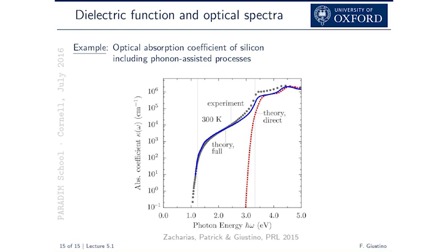And so essentially what it requires is all the things that we discussed so far for calculating band structures, phonons, dielectric constants, everything together basically, with an extra ingredient which is called electron-phonon interaction. So if you put all of this together, you can actually calculate the indirect absorption and get almost spectacular, perfect agreement with the experiment. But this is just to mention. So we managed to do this like last year. So that's very, very new. Until recently, it's been basically impossible to do this kind of calculation. So we're getting there, but it's on the advanced side, where the electronic structure community is trying to push to gain ground where we didn't manage to go before.